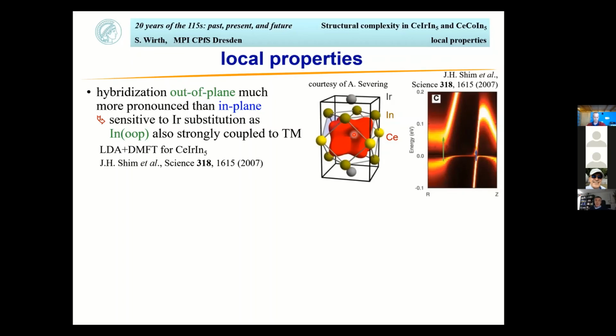And already in his paper, he pointed out that the whole thing is very sensitive to iridium substitution up here, because these indium atoms here not only strongly couple to the cerium, but also to the transition metal. So it is conceivable that if the transition metal moves here to the corner, note this is a different view as I've shown before, then one might have different hybridization.